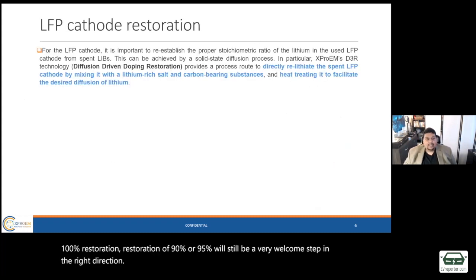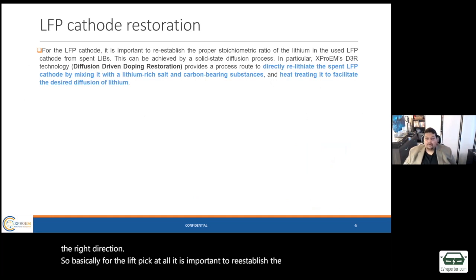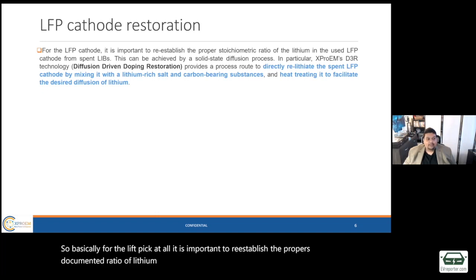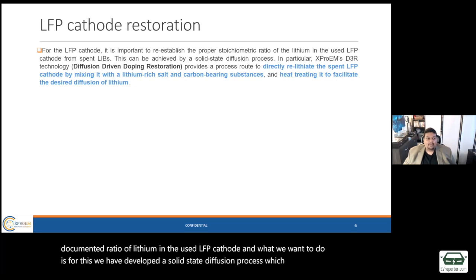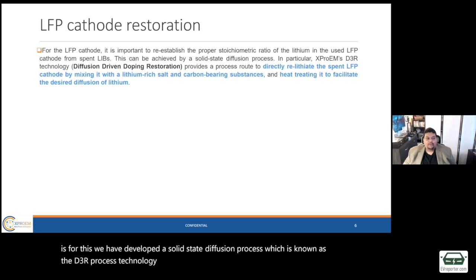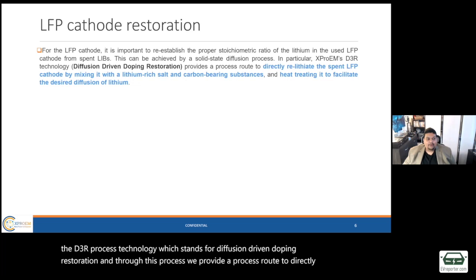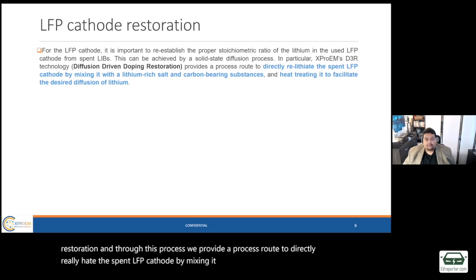So basically, for the LFP cathode, it is important to re-establish the proper stoichiometric ratio of lithium in the used LFP cathode. For this, we have developed a solid state diffusion process, which is known as the D3R process technology, which stands for diffusion driven doping restoration. Through this process, we provide a route to directly re-lithiate the spent LFP cathode by mixing it with a lithium-rich salt and carbon-bearing substance, and then we heat treat it to facilitate the desired diffusion of lithium back into the crystal.